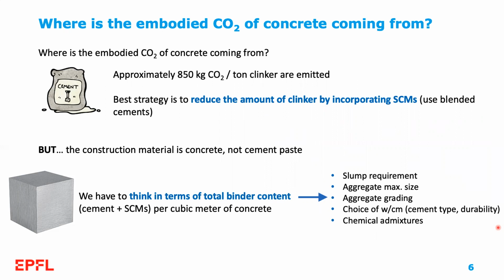But, and I want to be very clear, the construction material is concrete, not cement. And it's very important here that at the end of the day, we need to think in terms of total binder content, which is cement plus SCMs per cubic meter of concrete. And this is a multi-factor problem because this quantity depends on a lot of other requirements such as slump, maximum aggregate size, the aggregate grading that I use, my choice of water to cementitious material ratio, depending on the strength and durability requirements that I may have, and the use or not of chemical admixtures. So at the end of the day, this is a multi-factor problem. And in this regard, the performance of our blended cements is key, as I will illustrate in the next slides of the presentation.